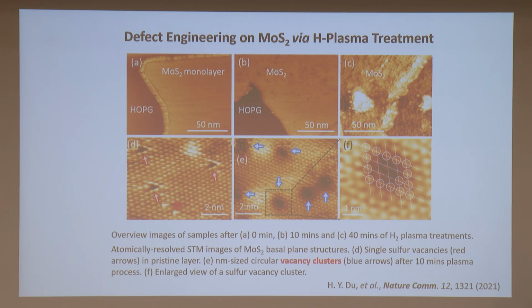you cannot get 100% perfect. You will also get some vacancies, but mostly they will be scattered single vacancies. So this is the single vacancy in the monolayer. Now, if you do plasma treatment, you will start to see clusters of vacancies. So you see, if you enlarge this, this is a few-vacancy cluster. Okay.